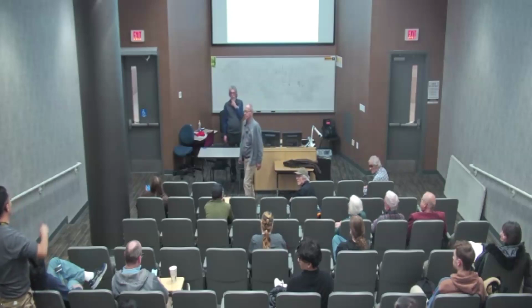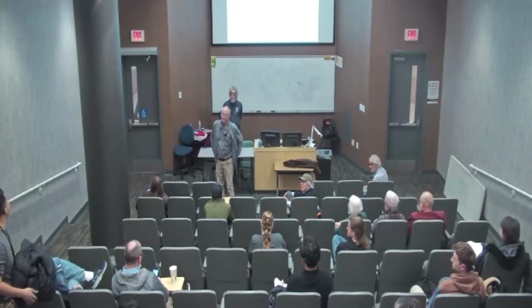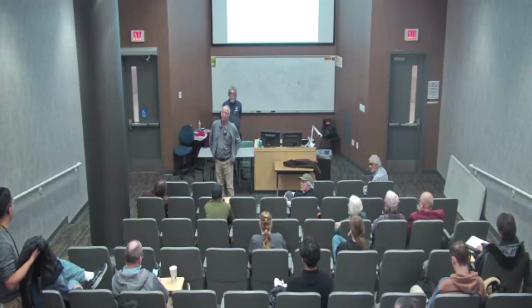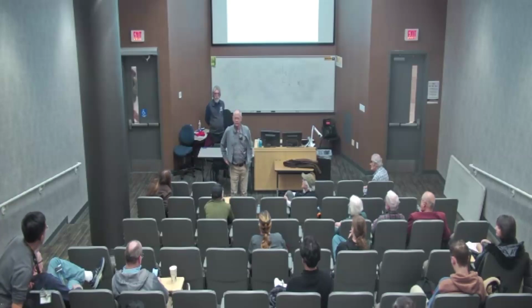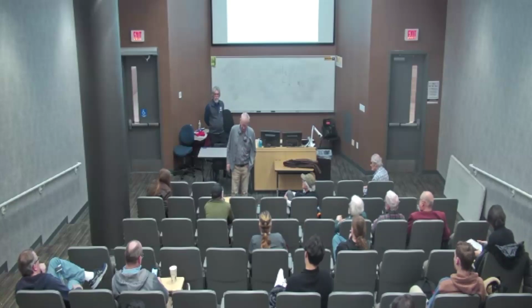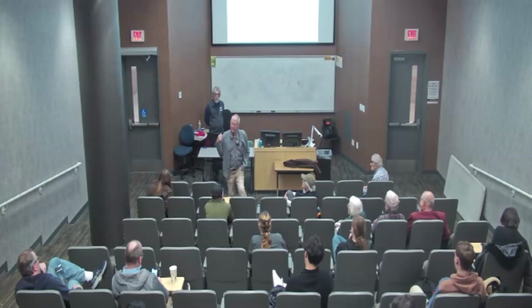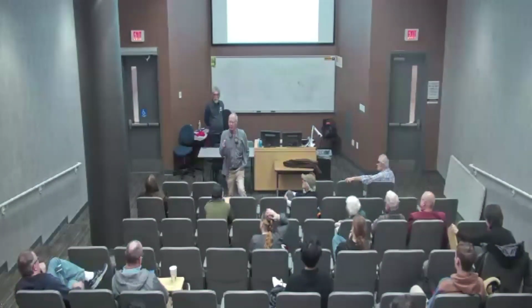So my question is about BCS theory. So BCS theory is still working with people, right? Yes, BCS theory still works very well. Actually, there's a strong coupling generalization of it, but it still beats what people call BCS theory. And it works very well for these metal hydrides. And when hydrogen sulfide was discovered to be superconducting at 160 gigapascal and 200 Kelvin, I believed it immediately.